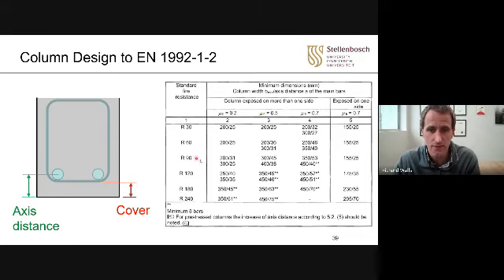So for instance, this is a table, and if you need a 30-minute, 60-minute, 90-minute, 120-minute structural resistance for different utilization factors, and the utilization factor is how heavily loaded is the column or beam in fire relative to normal. So normally your fire loads are roughly 50% of your ultimate loads. Not going to go into detail on how you calculate that, but often we're around there. Sometimes there are differences.